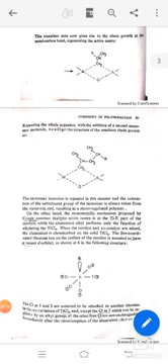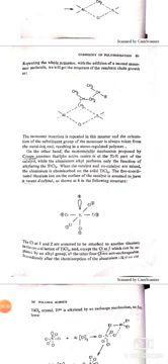When the catalyst and co-catalyst are mixed, the aluminum is chemisorbed on the solid titanium trichloride. The 5-coordinated titanium ion on the surface of the catalyst is assumed to have a vacant d orbital, as shown in that. This is the vacant d orbital. The chloride 1 and 2 are assumed to be attached to another titanium in the crystal lattice of titanium trichloride and except for the chloride at 5, which can be replaced by an alkyl group. All the other 4 Cl are non-exchangeable immediately after the chemisorption of the aluminium alkyl on the titanium trichloride crystal.